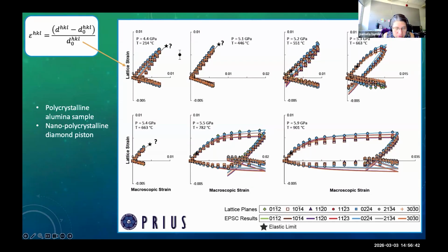And this is another thing, as you can see in the experiments, all the peaks don't go back to zero lattice strain. They're all over the place. So by the time we've done a full compression and decompression cycle, we have all kinds of residual stress in the sample. The stress state is really quite complicated, which is why we anneal. I think it's probably because in this model you don't consider possible grain overlap, because every grain was treated like an ellipse.